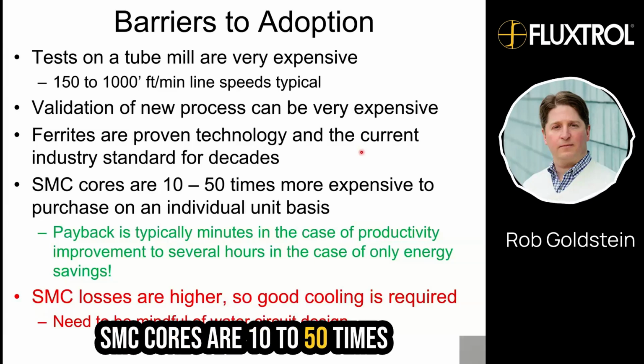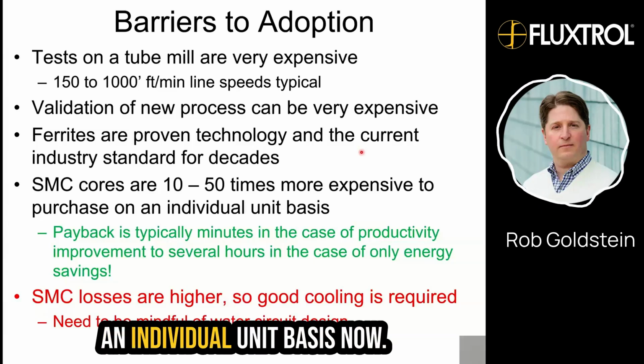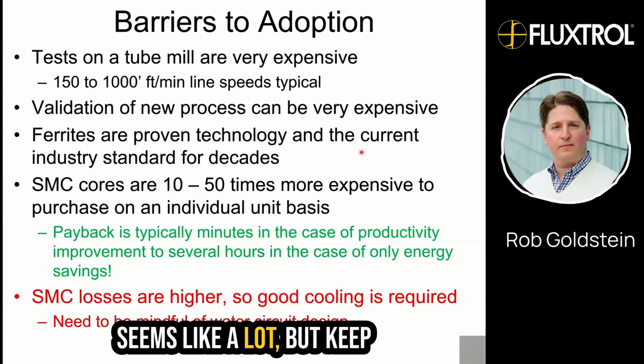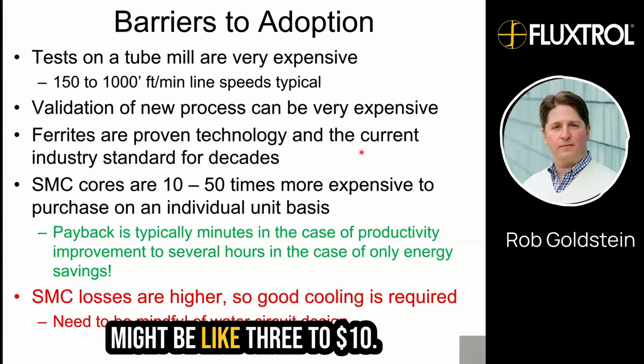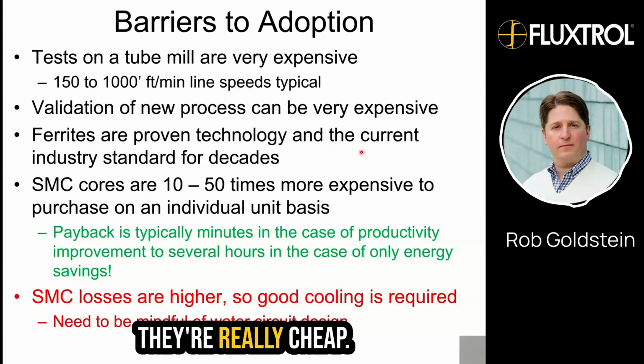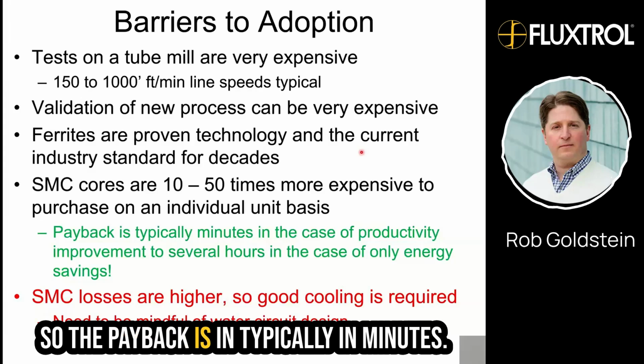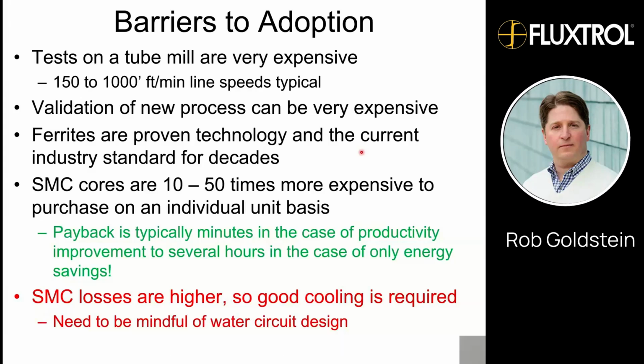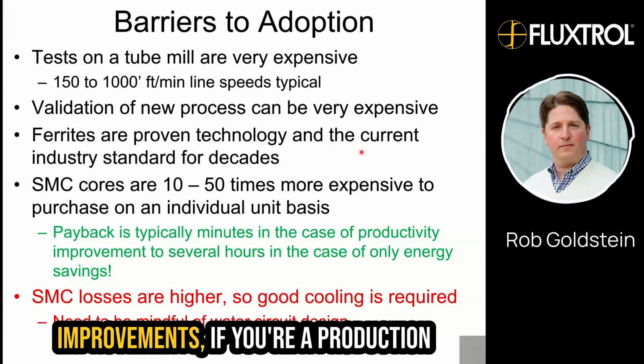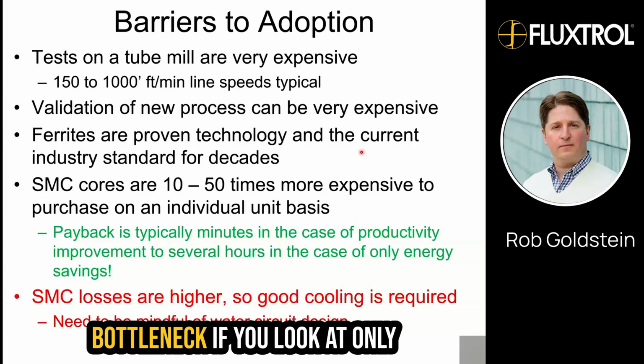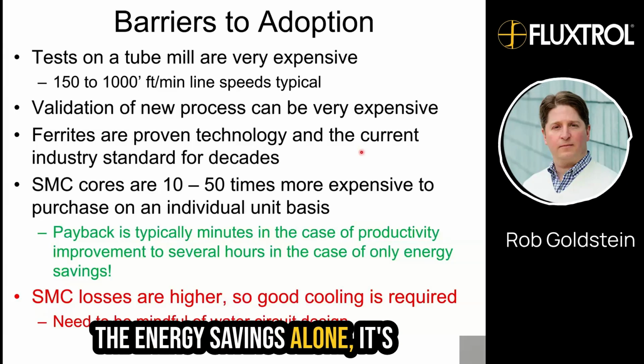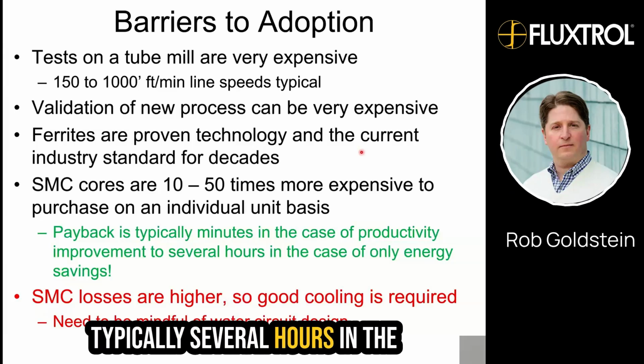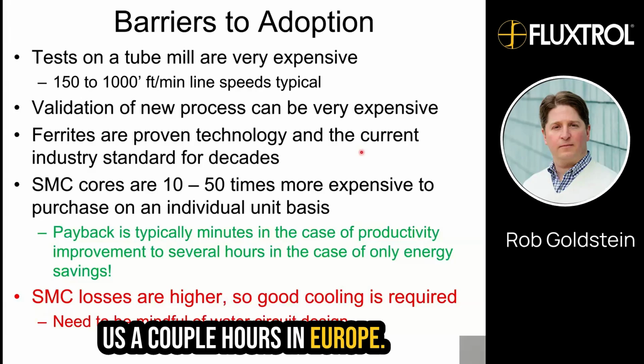SMC cores are 10 to 50 times more expensive to purchase on an individual unit basis. Now, that seems like a lot, but keep in mind the normal ferrite might be like $3 to $10. They are really cheap. So the payback is typically in minutes. If you look at the productivity improvements, if you're a production bottleneck, if you look at only the energy savings alone, it's typically several hours in the US, a couple hours in Europe.